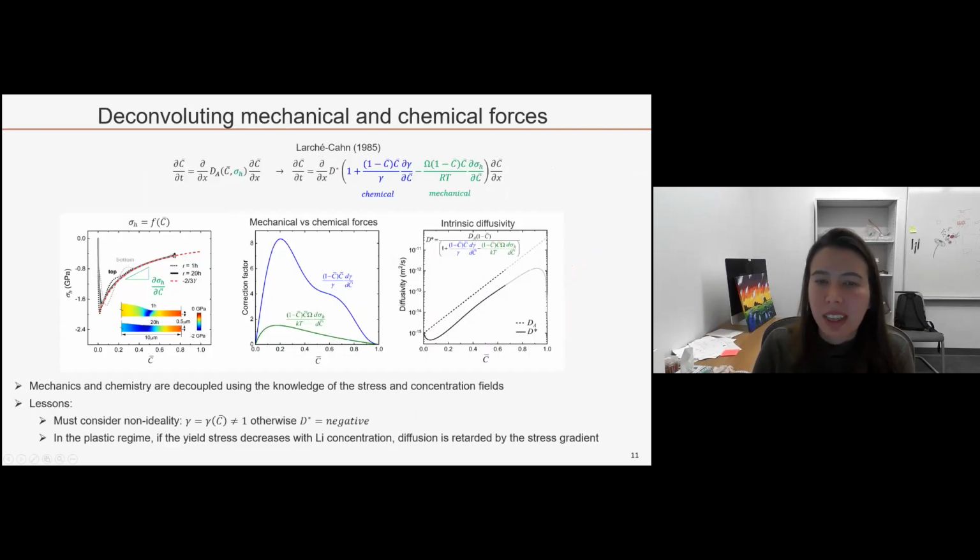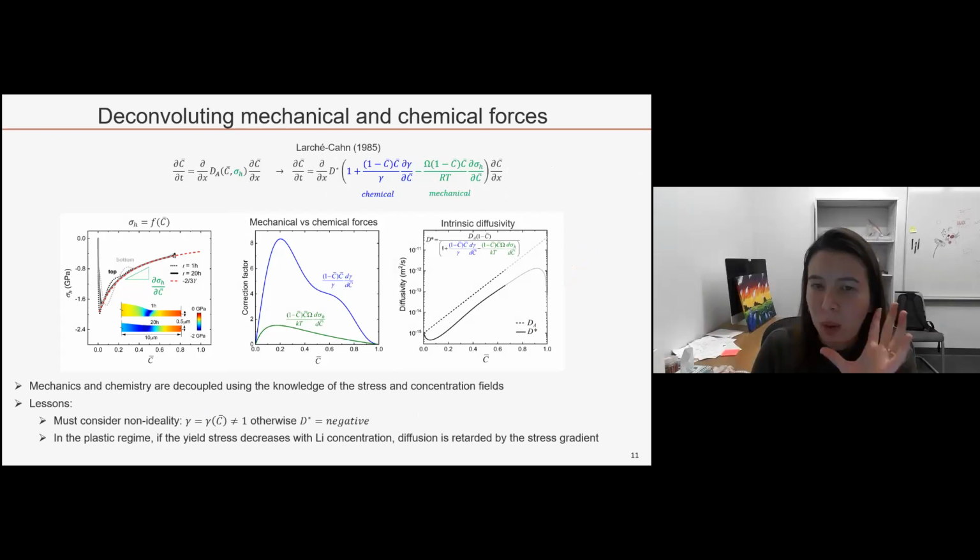What I found out is that this equation really doesn't explain this behavior in all boundary conditions. If I change the boundary conditions, then my results didn't match. So what I had to do is consider a more complete method, which is an old method, the Larché-Cahn method, which includes the stress gradient as a driving force in addition to the chemical driving force for diffusion.